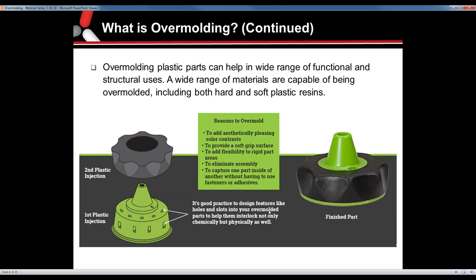Anytime you're trying to overmold one material over another, it's always good to plan ahead and provide design features within the substrate — holes, reservoirs — any area that will help hold on to that material and keep it bonded to the substrate. You want a good chemical bond, and in most cases you can get that, but you also want a physical locking bond. Determining the two different materials — it's always good to get an expert opinion from material suppliers, technicians, and engineers. They can help with the specifics on what materials bond best together, since some don't bond as well to others.